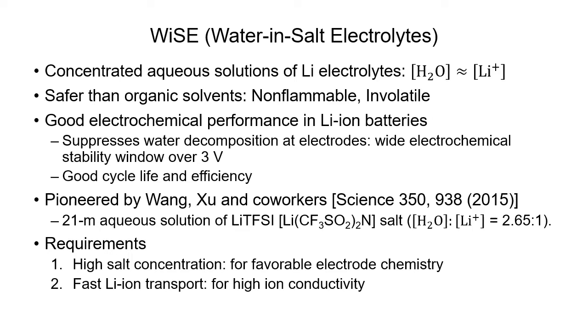In this work, I studied an electrolyte solution called WISE, that is water-in-salt electrolytes. It's a concentrated aqueous solution of lithium electrolytes with comparable concentrations of water and lithium ions, and it's safer than organic solvents used in conventional lithium-ion batteries, and also it has a good electrochemical performance. It was proposed by Wang Xu and co-workers in 2015. They used this lithium TFSI salt dissolved in water with a saturation concentration of 21 molality.